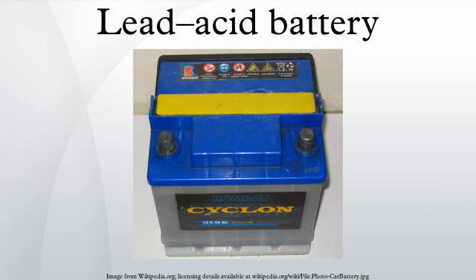As batteries cycle through numerous discharges and charges, some lead sulfate is not recombined into electrolyte and slowly converts to a stable crystalline form that no longer dissolves on recharging. Thus, not all the lead is returned to the battery plates, and the amount of usable active material necessary for electricity generation declines over time. Sulfation occurs in lead-acid batteries when they are subjected to insufficient charging during normal operation. It impedes recharging. Sulfate deposits ultimately expand, cracking the plates and destroying the battery.